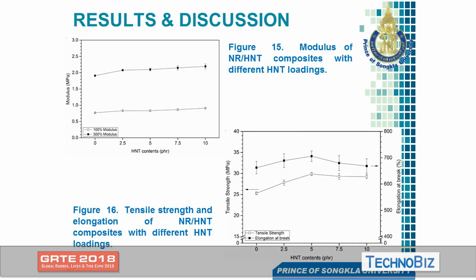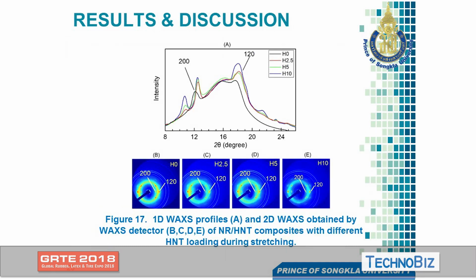This is the tensile strength, which increases with the increasing loading. This is the result from the wide-angle X-ray. We scan from 2 theta equal to 8 to 20 something, and then we see the strain-induced crystallization.